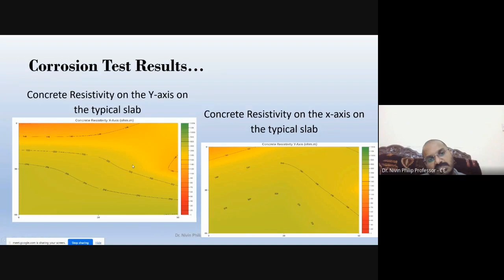So by doing this concrete resistivity test, we can identify where the concrete quality is low. At that point only, we have to rectify it. So we can rectify only the required portion by identifying this contour. For the remaining portion, which is a slight greenish color, maybe we can avoid any repair work, or we can do some painting or something. A simple solution is sufficient to prevent further propagation of moisture.